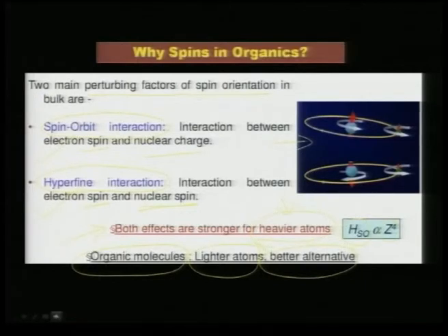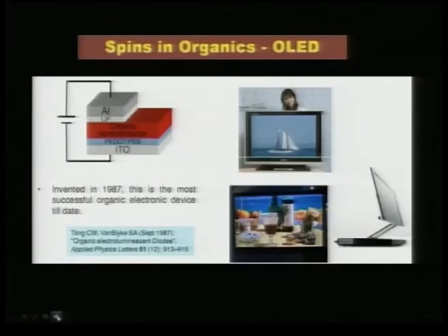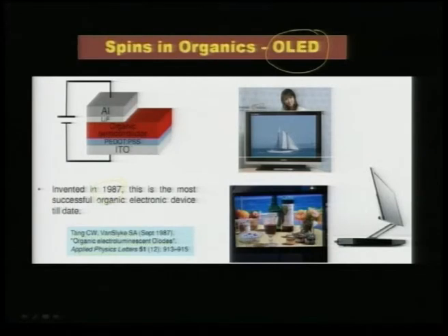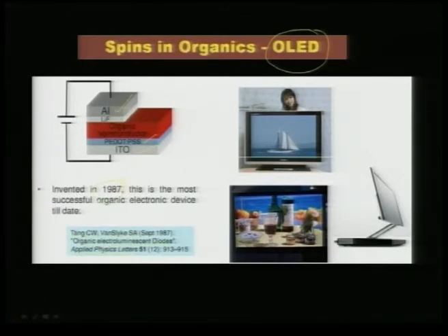Where do organics come into picture in electronics? The classic example is that of organic LEDs. In 1987, it was VanSlyke and Tang who reported organic electroluminescent devices in Applied Physics Letters. The typical organic LED configuration has a transparent ITO layer compounded with PEDOT:PSS, which is a hole-doping layer, and aluminum as cathode with a small lithium fluoride barrier. If this sandwiches an organic semiconductor, light comes out of the ITO layer, bringing about a new generation of display devices.